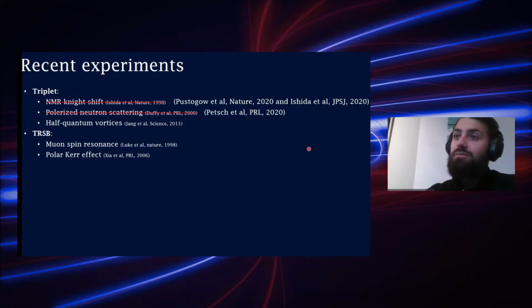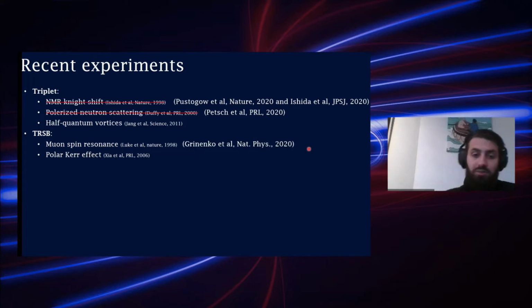Then again, the muon spin resonance experiments have also been revisited in strained samples, or while straining the sample, and it was actually found that this is still standing.